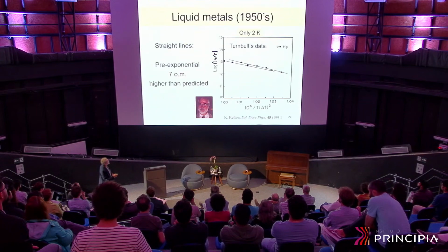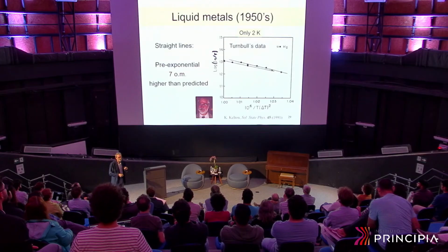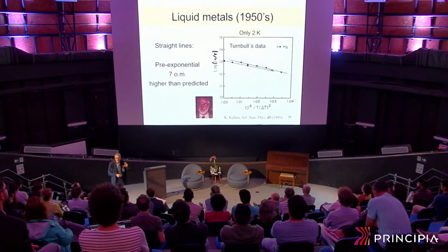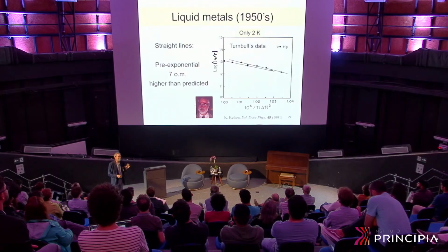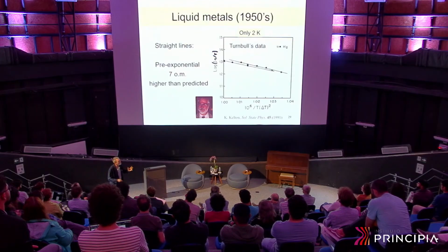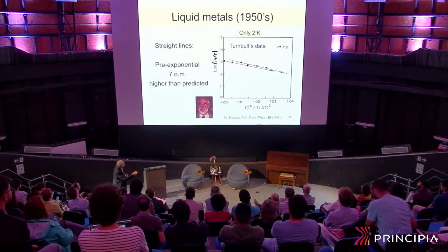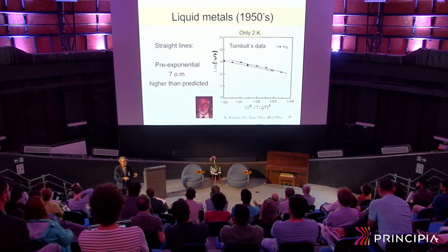Guess what? 7 orders of magnitude discrepancy. Not 7 times, but 7 orders of magnitude. People said, well, but these experiments were very crude. They were measuring only 2 degrees Kelvin, a very long extrapolation, so they're not a definitive test of the theory.